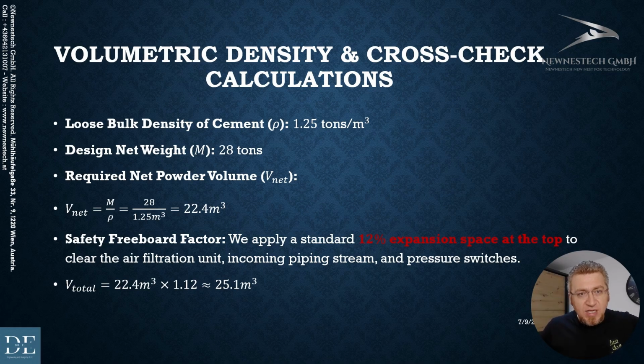Now let's check the volumetric density and also the dimensions. For the cement, the loose bulk density will be close to 1.25 tons per cubic meter because of the entrapped air. And since we are considering 28 tons of cement, with the density that we already mentioned, the volume should be at least 22.4 cubic meters. We will add a 12% expansion space at the top, which is important for compensating any changes in the pressure during the filling especially, so we end up with 25.1 cubic meters. And this is the volume that we will use as a base for sizing the diameter, the height, and other parameters. In the next slide, we will see how we will deal with it.